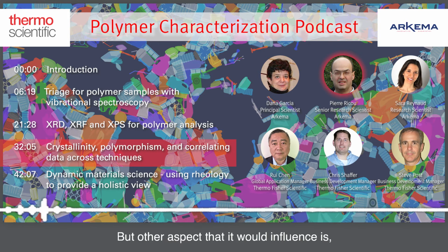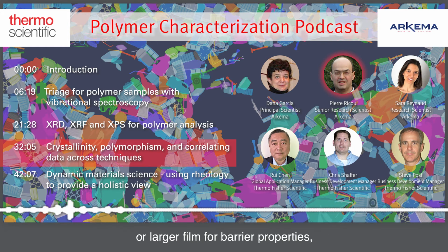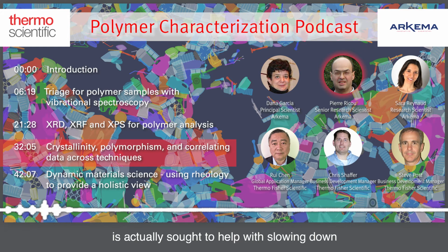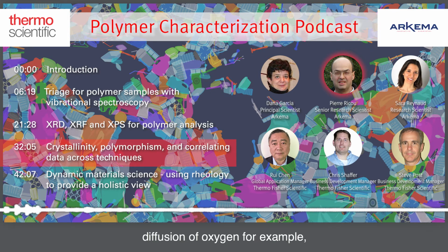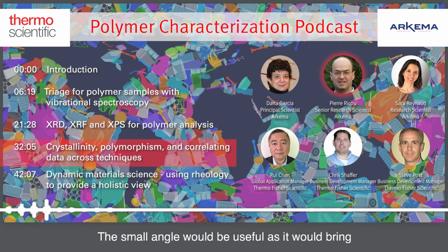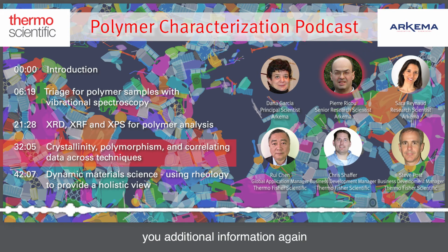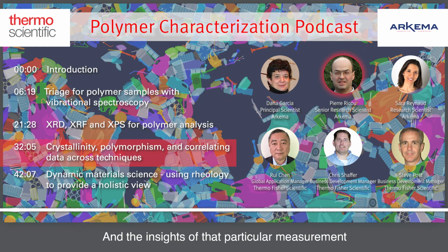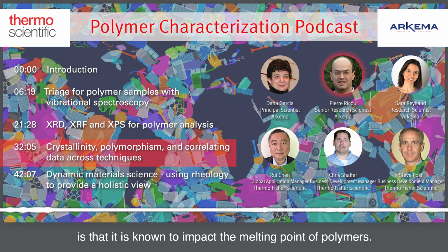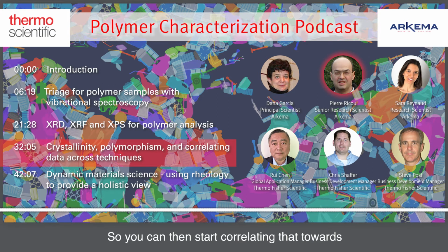Another aspect it would influence is, if you're developing a film for barrier properties, a higher crystallinity is thought to help slow down diffusion of oxygen, for example, through the polymer film. The small angle would bring you additional information about the lamellae dimension, in particular the lamellae thickness. The interest of that measurement is that it is known to impact the melting points of polymers, so you can start correlating that to data from other techniques, thermal techniques in particular.